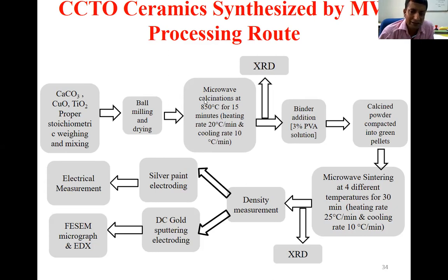In the heating temperature and heating duration, as in the conventional process, it's near about 4 hours. So both the heating temperature and heating durations were reduced. And similarly, for the sintering, we sintered the samples for 30 minutes at 1000, 1025, 1050, and 1075 degrees Celsius. And this heating rate was of course 25 degrees Celsius per minute. So the heating cycle is very small.